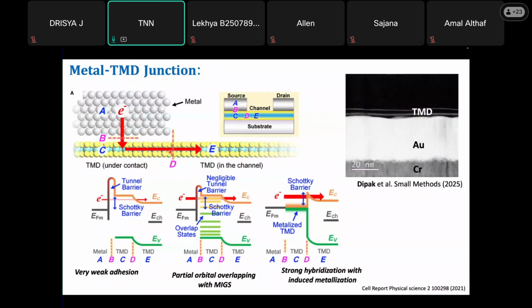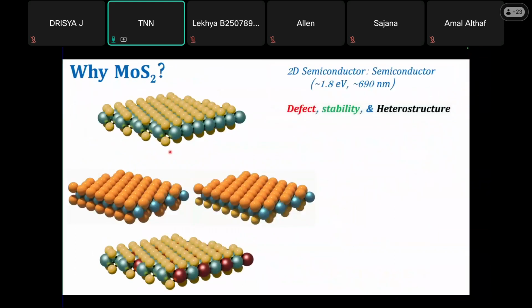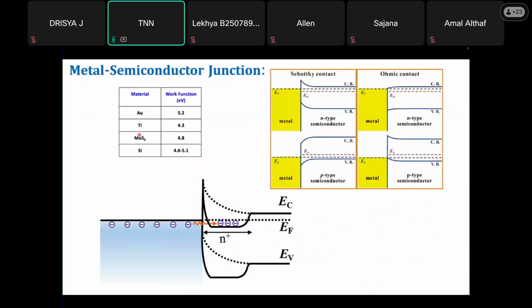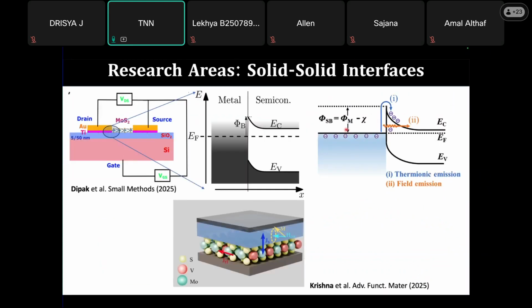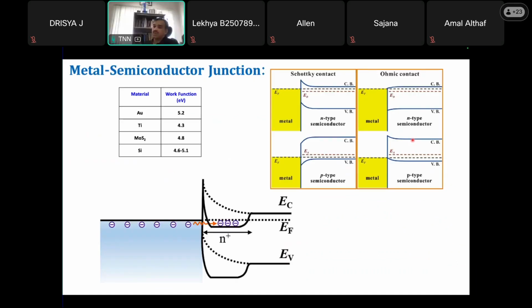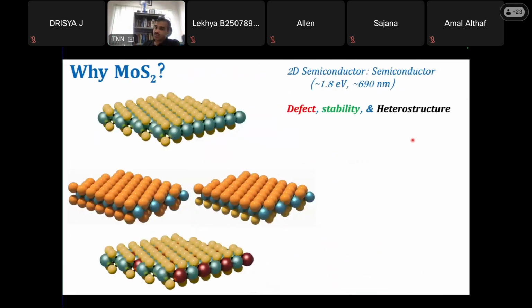I told you about the Schottky barrier, and very nicely you can choose the semiconductor or the metal by looking into their work function. These are ideal cases where the barrier phi SB follows phi M minus chi. In many cases, if there is a defect in the semiconductor, the metal site will get pinned into a particular defect site. So even if you vary the metal, this will not follow phi SB equal to phi M minus chi. So there won't be any relation like this. It will be a problem. In most cases, a semiconductor without defects is quite hard to develop. And this is the case with two-dimensional materials also.